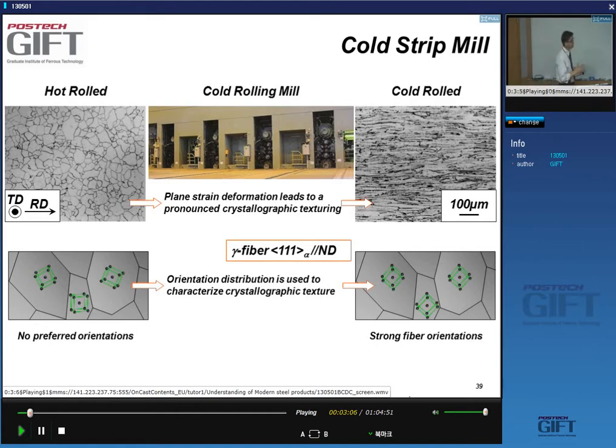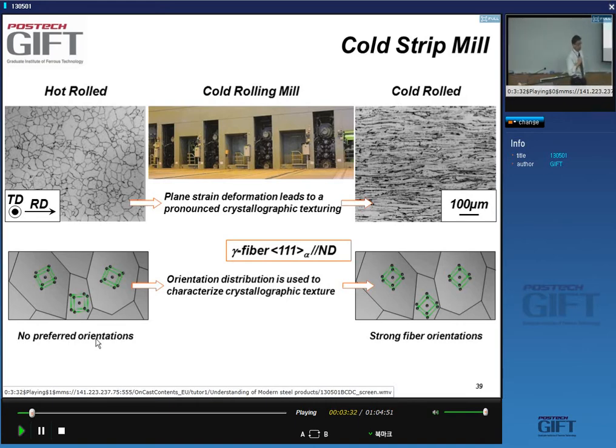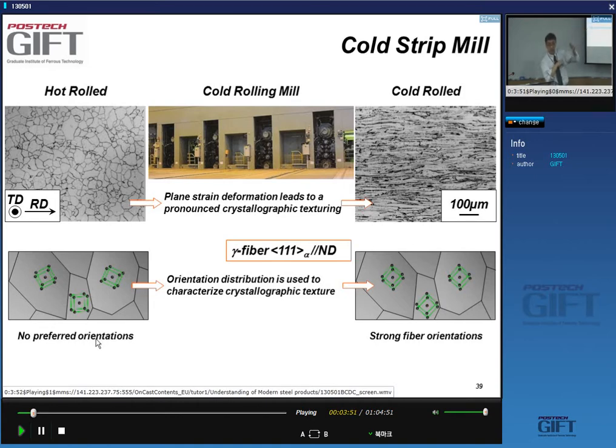In contrast to the hot strip mill, where you end up with a hot rolled material that is fully recrystallized, in the case of the cold rolled mill, you have heavily deformed material. The amount of strain applied here is very much larger — for example, making a tensile specimen achieves maybe 20-30% deformation, whereas in cold rolling you easily achieve 70% or more. It is very heavily deformed, very hard material with no plasticity.